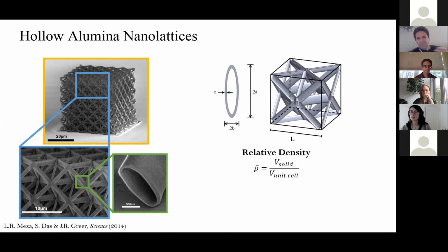So we have now a very lightweight structure that has some new mechanical property scaling depending on exactly what architecture it's in and what it's made out of. So you have the constituent property of the material and then some function of relative density for strength and stiffness, for toughness and other properties. It scales differently. So this was some of my early work.